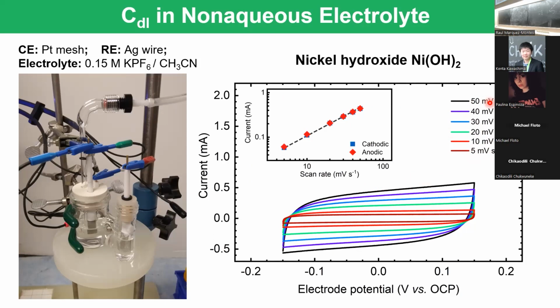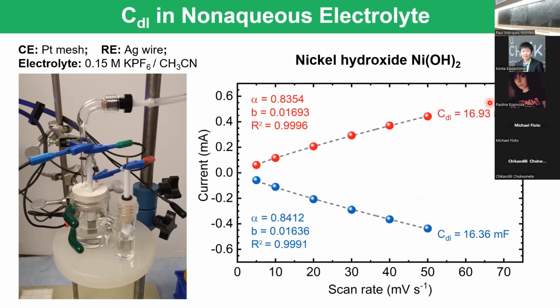So actually, I'm not showing these results today because we did these experiments last week. But the way we were able to solve this issue was oxidizing the material. Because when you oxidize nickel 2+ into nickel 3+, nickel oxyhydroxide is a better conductor than nickel hydroxide. So we were able to get really nice data. But unfortunately, I didn't have enough time to plot all the results for today. But yeah, that's the main way we can use this technique.